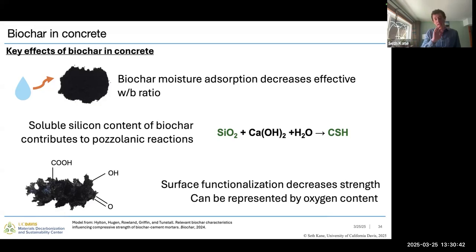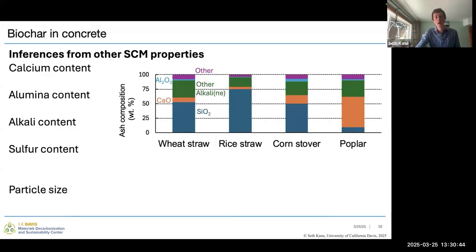And so these are the three properties that came out of that exact model, but we also can make some inferences about what might be the best feedstock by thinking about what we want in supplementary cementitious materials pretty broadly. So if we think about our different inorganic compounds, our calcium, and specifically our calcium to silica ratio in our SCMs, our alumina content of our SCMs, different alkali and alkaline compounds that might be participating in those cementitious reactions in potentially a detrimental way, our sulfur content.